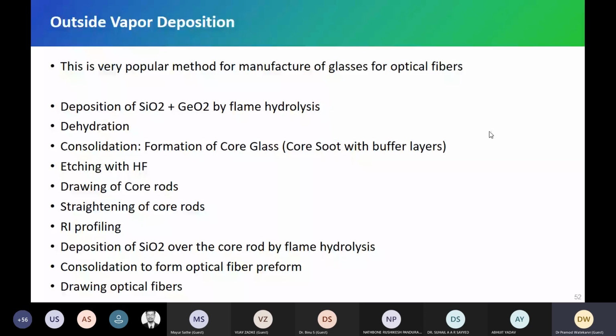So that's the advantage. So, that's why companies are using OVD. But people are using VAD also, because the advantage is it can produce more kilometers of fibers as compared to OVD, and it is a one-step process, so it is very fast. In axial deposition, we have core plus clad at a time. In OVD, we first make the core, SiO2 GeO2 is deposited first. We make the glass out of it, and then we take that glass and again deposit SiO2 over it, that forms the cladding. So it is a two-step method, so time needed is more.